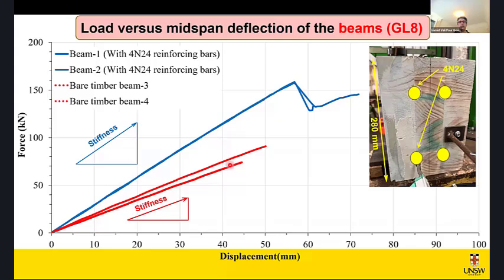And you see the red one is the load displacement of the unreinforced beam, and the blue one is the reinforced beam. One thing I would like to draw your attention to is the difference between the peak load of these two versus the peak load of these two. You see, when we have reinforcement in the cross sections, the variability in the peak loads reduces quite a lot, and also in the stiffness.